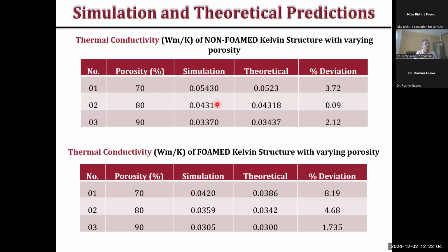So when we say non-foamed, meaning all these struts are made up of a solid material system. And here, when we say foamed, the strut itself is a foamed one. Now, before going into the manufacturing side, we wanted to know what level we can reach with the porosity level increase. And when we compare foamed and non-foamed, the theoretical values are somewhere around 0.03, which is what we estimated using our simulation and analytical background.